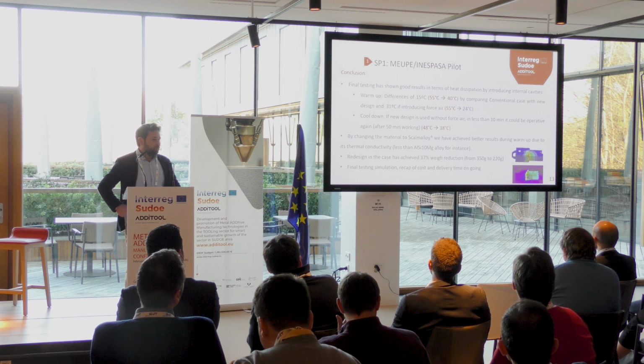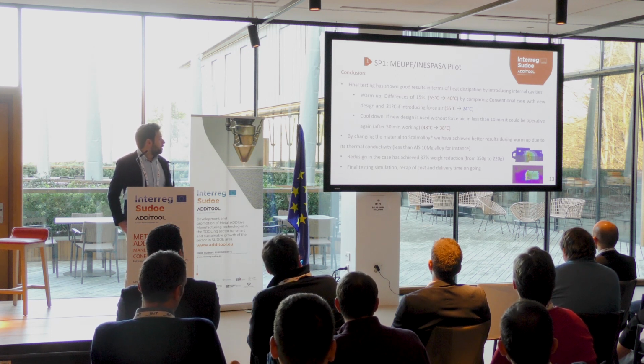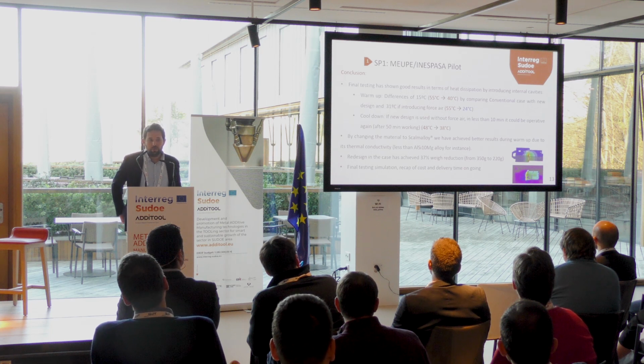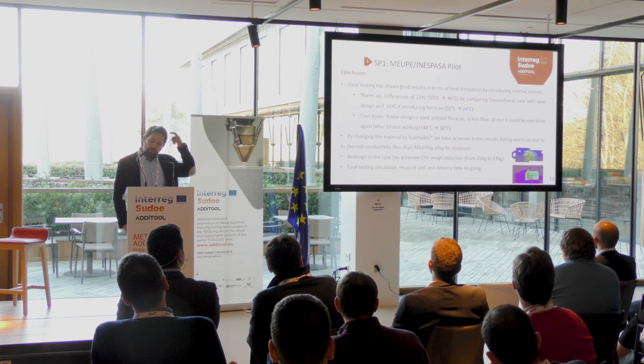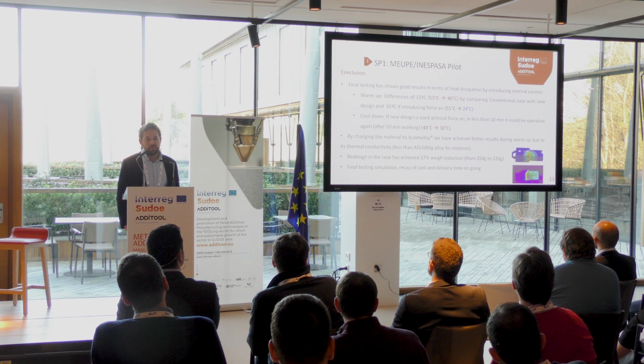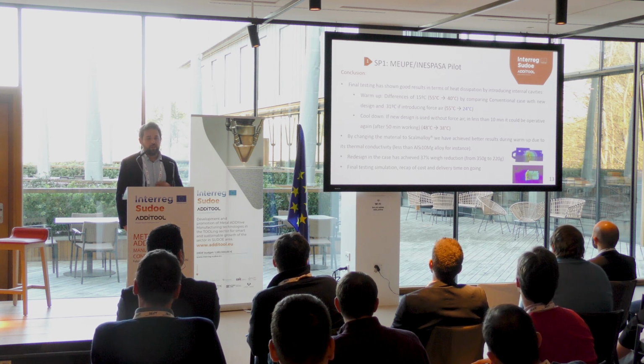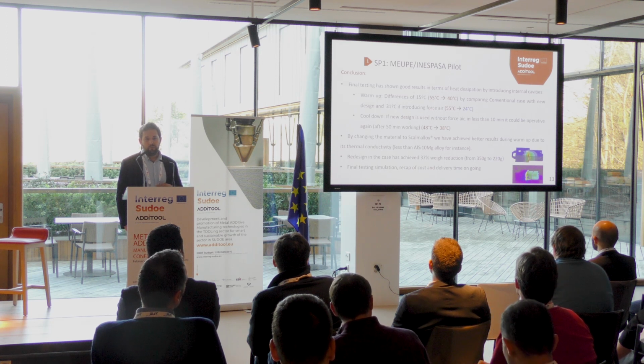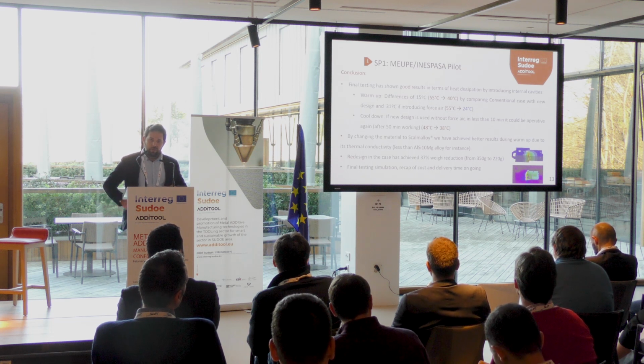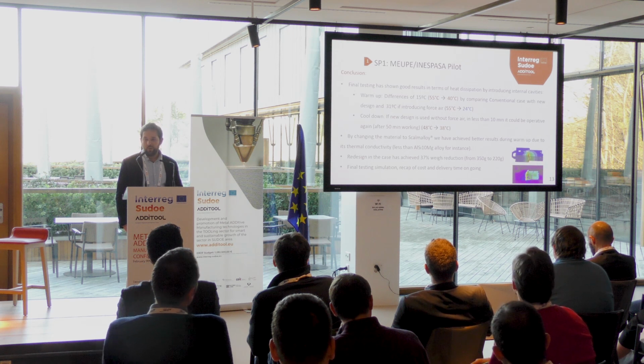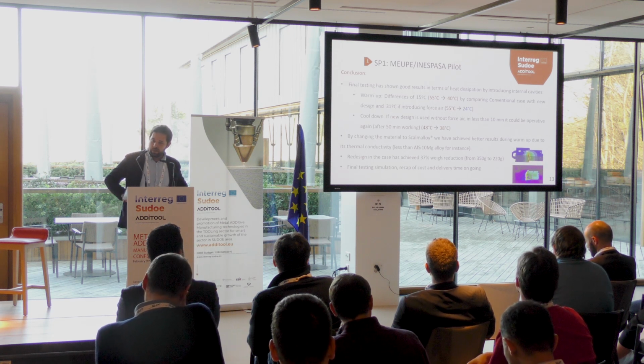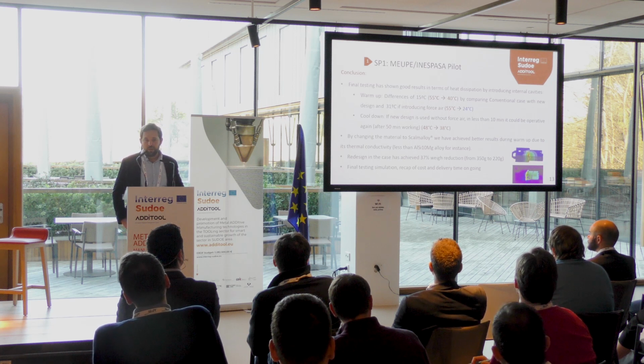So main conclusion: the final testing has shown really good results in terms of heat dissipation. In terms of warming up, we reach a difference of 15 degrees if we only compare conventional with the new design. But if we put air, we reach a difference of 31 degrees. And working with that case without air, in less than 10 minutes it could be operative again, after 15 minutes of working.